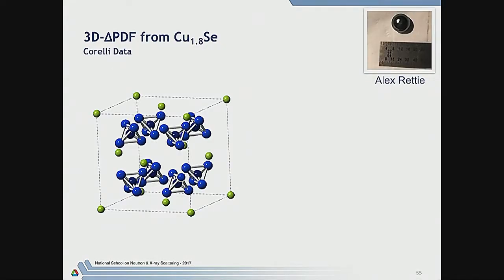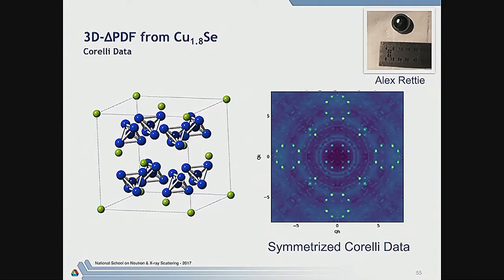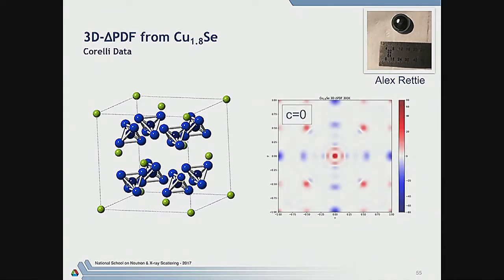But if we do this 3D delta PDF technique, here are all the atoms in the unit cell. So some of the copper ions are at these quarter-quarter-quarter positions. Others are distributed on these tetrahedra. Here's the symmetrized data with a lot of powder peaks and various things like that. But if you do the PDF, you end up with, again, sets of spots representing possible interatomic vectors. In particular, you can see that if this quarter-quarter-quarter is occupied, this three-quarters-quarter-quarter is not going to be occupied because it's blue.